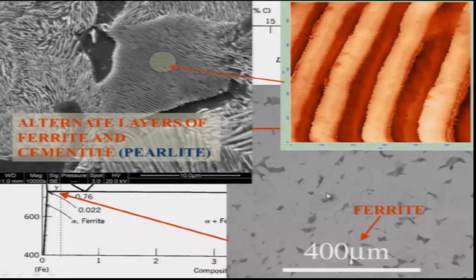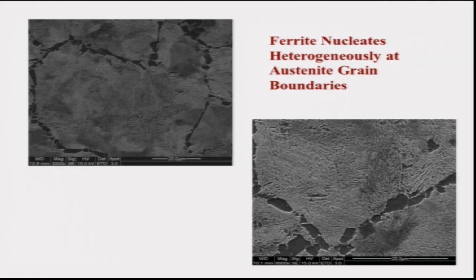So, whether it is austenite to ferrite transformation, it is a diffusional transformation, one can study it from the perspective of the Avrami relationship and determine what the parameters n and k are experimentally, as we will soon see how. In these micrographs, one can also see that the ferrite is these dark regions all around, and inside here is pearlite.